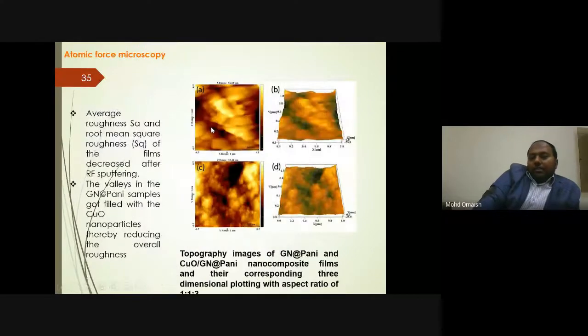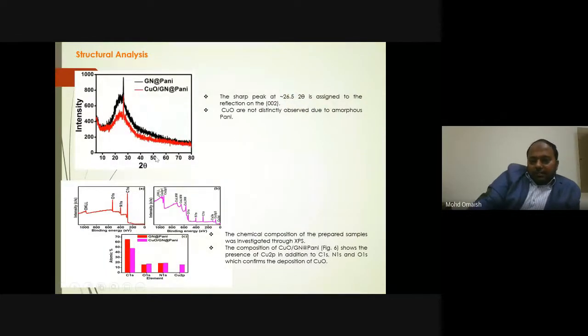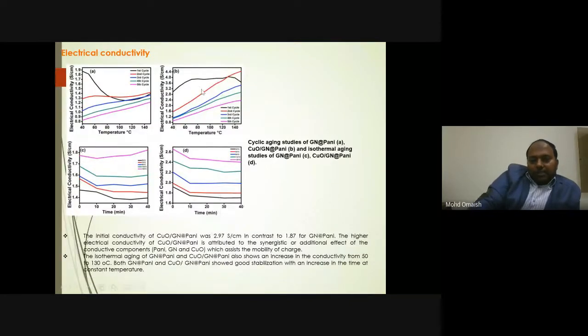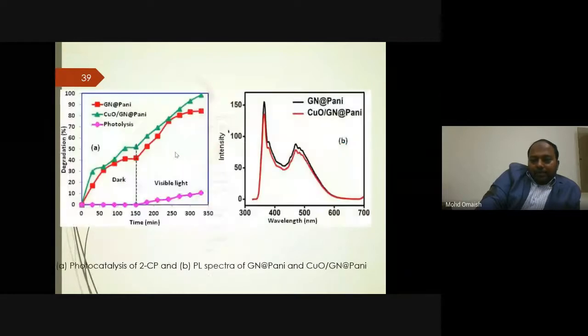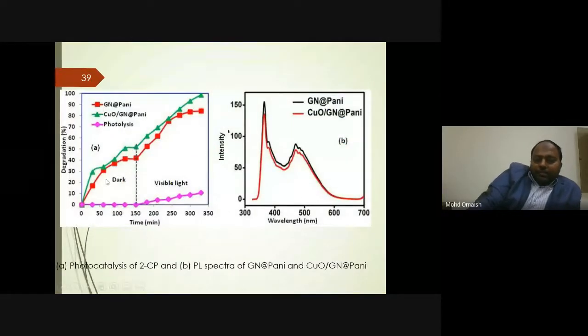And this SEM analysis also shows the copper oxide filling the valleys of the polyaniline and graphene. This is the XRD and XPS, which show successful formation. We similarly studied the electrical conductivity and aging to check the stability of our composite, and we did photocatalysis under visible light, and we got slightly improved photocatalysis results for our composites in contrast to polyaniline graphene.